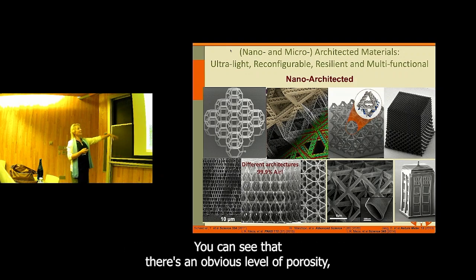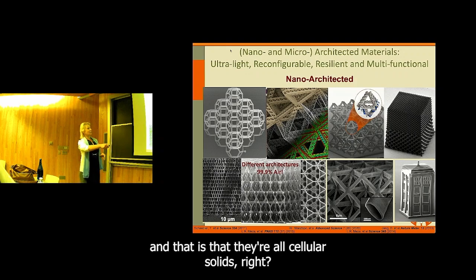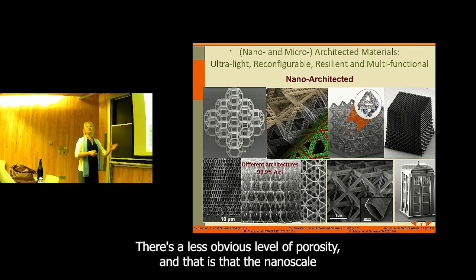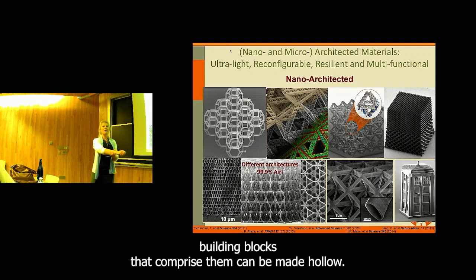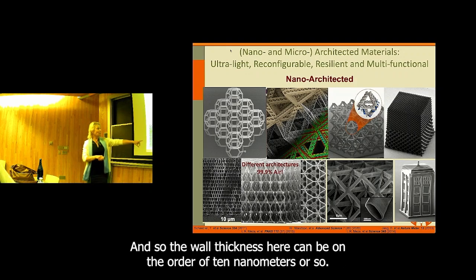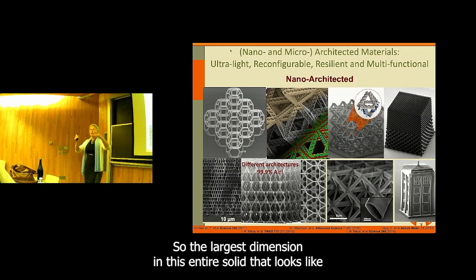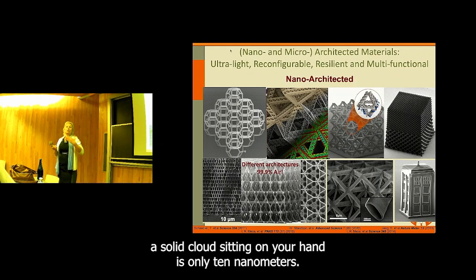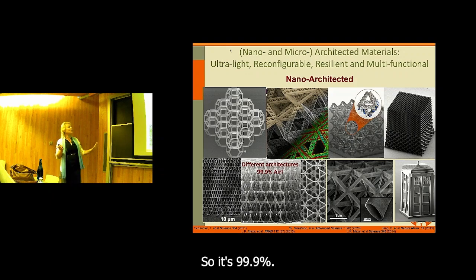You can see that there's an obvious level of porosity, and that is that they're all cellular solids, right? There's a less obvious level of porosity, and that is that the nanoscale building blocks that comprise them can be made hollow. And so the wall thickness here can be on the order of 10 nanometers or so. So the largest dimension in this entire solid that looks like a solid cloud sitting on your hand is only 10 nanometers. So it's 99.9% air.